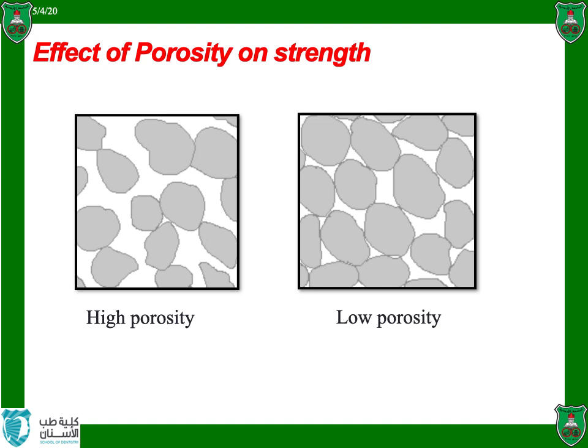The voids and porosity are factors that may reduce the compressive strength of amalgam, and the lack of plasticity of the amalgam mix, like delayed condensation or under trituration, will lead to porosity in the amalgam. And also insufficient condensation pressure on dispersed cut alloys will result in more porosity and decrease the compressive strength.